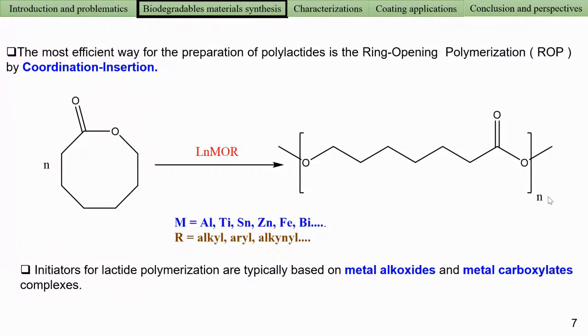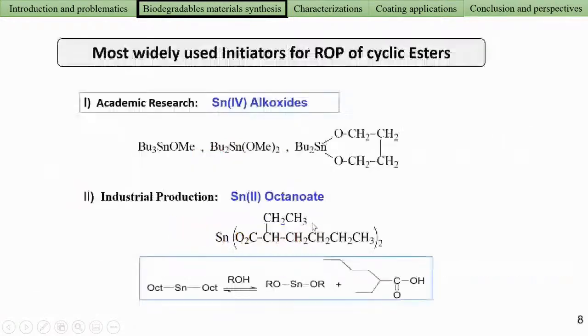The main method to prepare this polymer is ring-opening polymerization, and the catalysts that can be used are metal alkoxides based on aluminum, titanium, tin, zinc, iron, and bismuth. But the most useful catalyst, for both academic research and industrial production, is based on tin. For academic research, tin alkoxide is the most useful catalyst because butylated tin(IV) alkoxides are cheap, commercially available, thermally stable, and lead to really good control of the polymerization. We can prepare block and multi-block polymers with high molecular weight, and we can achieve specific end groups.